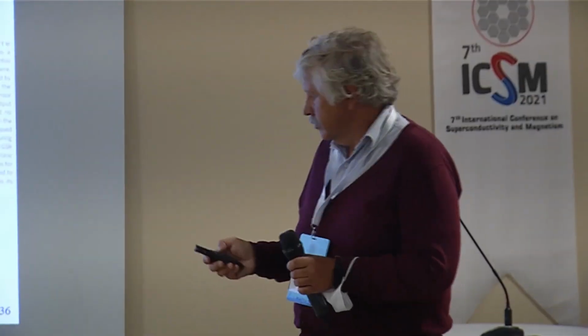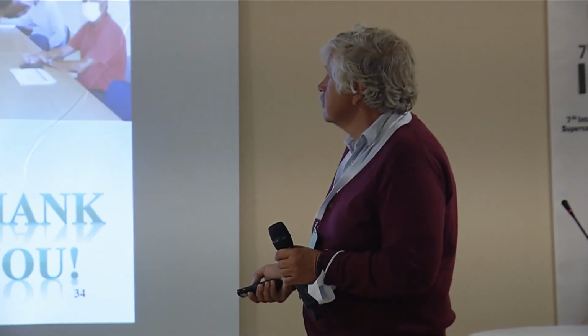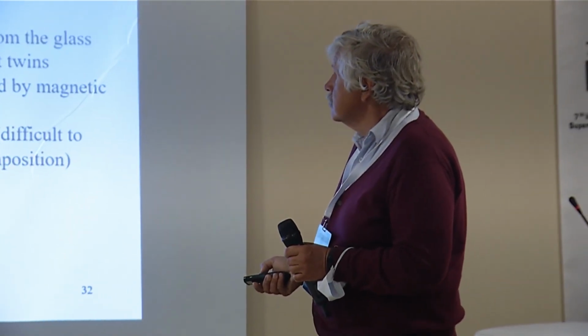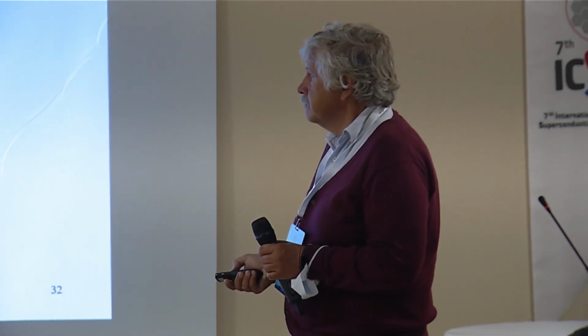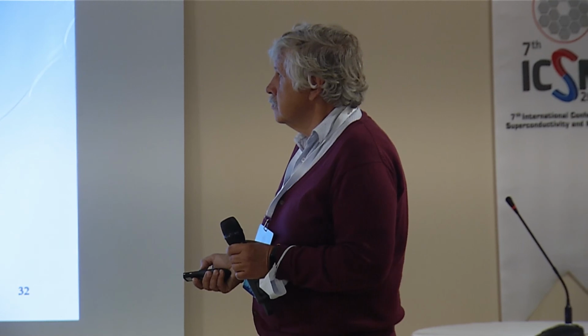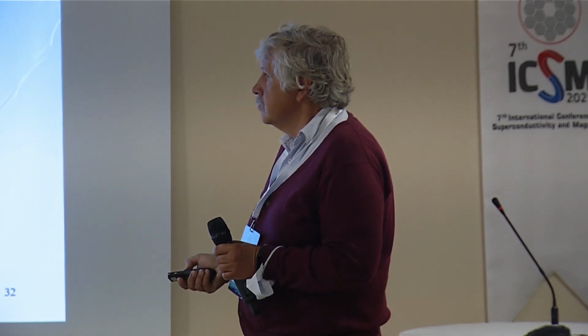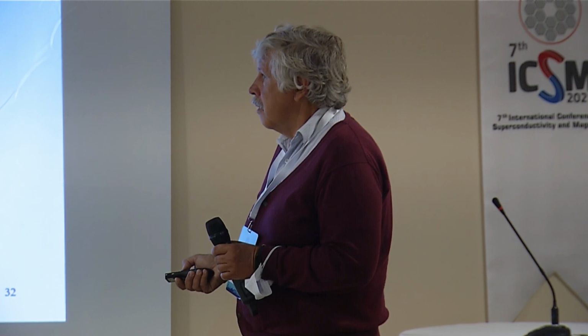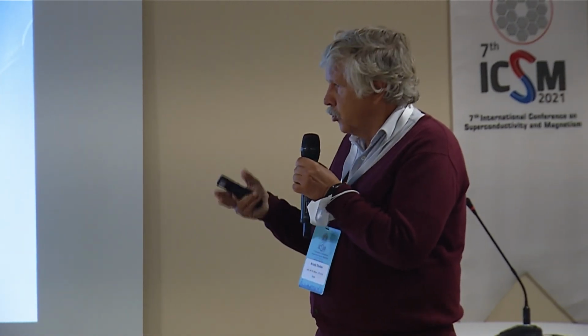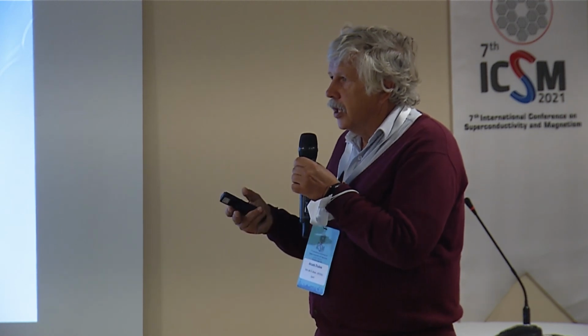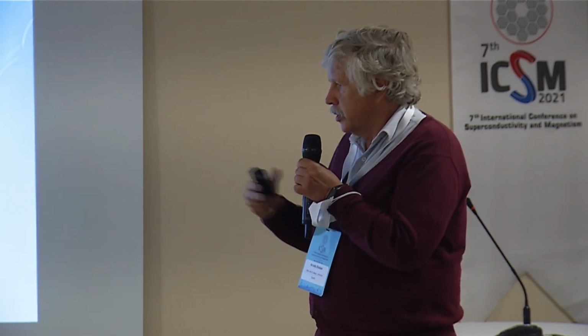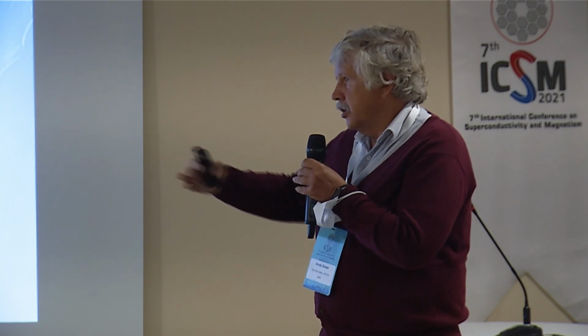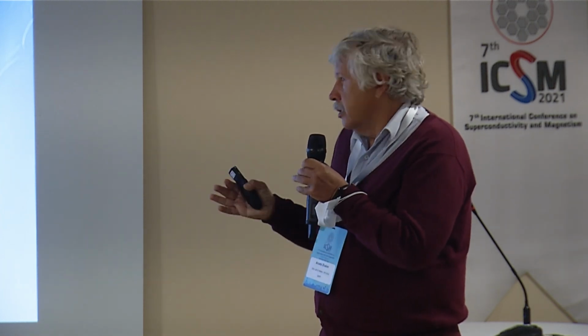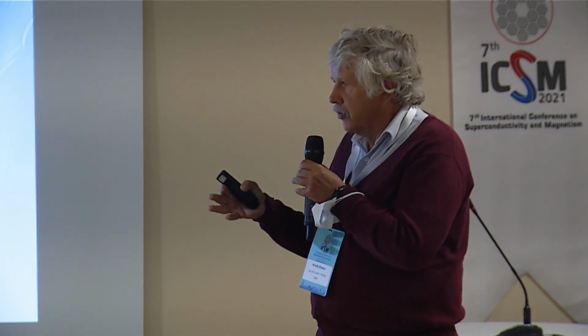Okay, just very short. One of the interests of these microwires is for magnetocaloric applications, as far as I understood. In which particular kind of applications do you think these microwires would be best suited compared to other kinds of materials? I think, in fact, it could be interesting for microactuators probably, or for a magnetic refrigerator. And in one of our first papers, we showed that glass, in fact, does not absorb the heat, but just the heat exchange becomes slow. And therefore, if we can achieve a high magnetocaloric effect, it could be suitable.